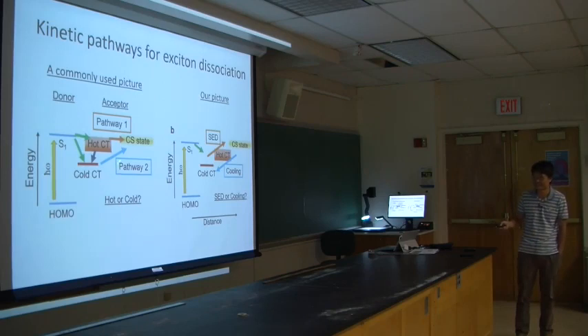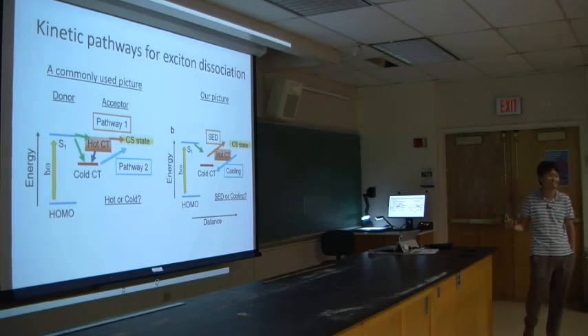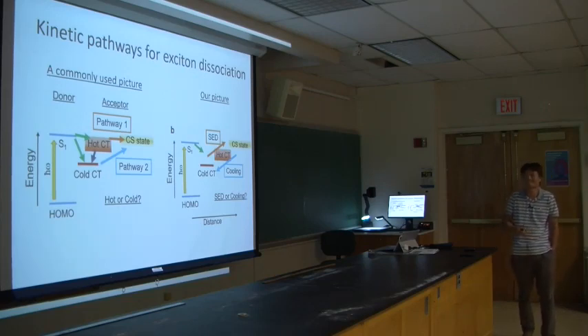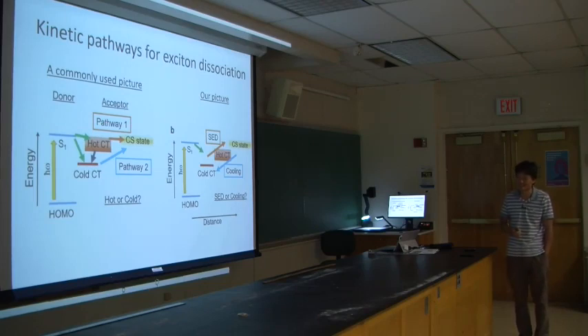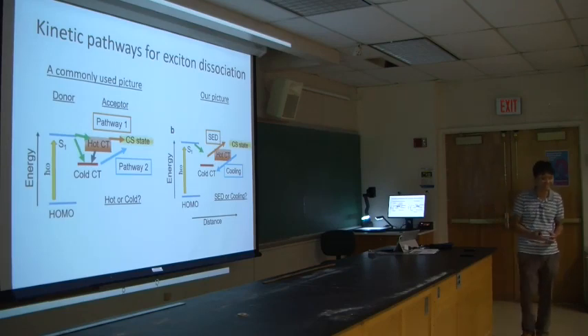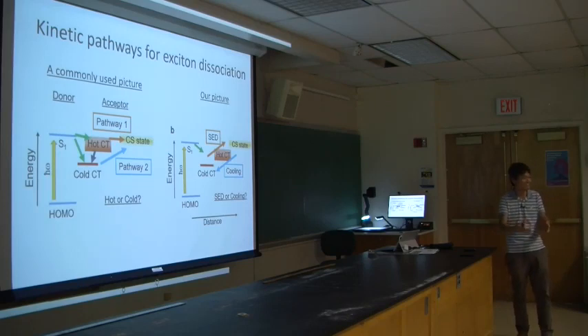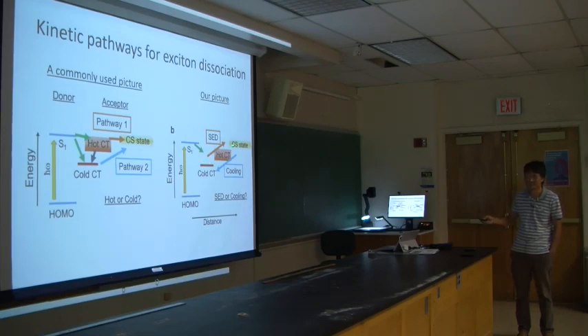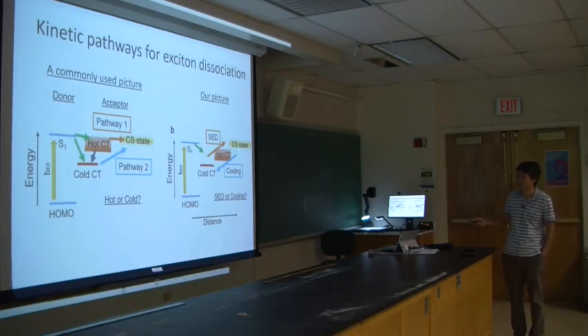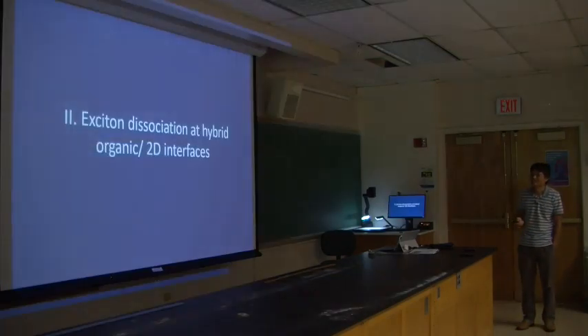Some results seem to show that the cold pathway is the only pathway that could be important. And in some work, they observe the CT state, and they observe very fast dissociation of this exciton, so they think the hot pathway is important. But I think this picture is not quite accurate in the sense that it's always assumed that you go down here. What we think is that it depends on the configuration of your interface. You could have some interface that really utilizes the entropy effect, which allows this cold state to go to the separated state simultaneously. Versus, you could have interfaces in which the entropy effect is weaker, and then this delocalized state actually localizes and becomes this bound CT state. So that's one of the conclusions we have.